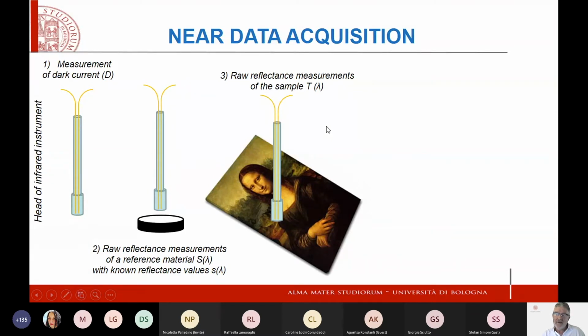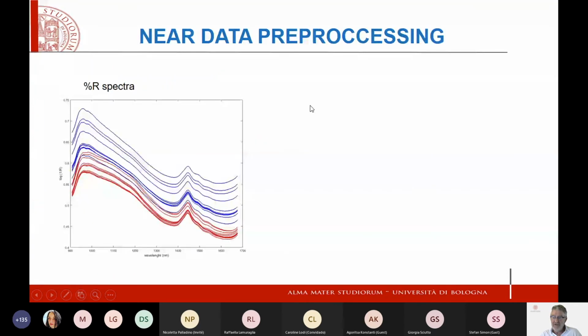How are the data acquired? The technique foresees the measurement of a dark current. Here you can see the head of the instrument, and then you need to collect the raw reference measurement of a standard sample with known reflectance values, and then you can go directly on your object and collect, without touching the object, in a non-invasive way, the near-infrared spectrum. What you obtain are spectra like this, which are, as I told you, very broad,